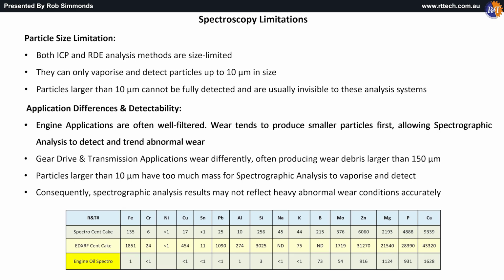Application differences and detectability. Engine applications are often well filtered. Wear tends to produce smaller particles first, allowing spectrographic analysis to detect and trend abnormal wear. Gear drive and transmission applications wear differently, often producing wear debris larger than 150 microns. Particles larger than 10 microns have too much mass for spectrographic analysis to vaporize and detect. Consequently, spectrographic analysis results may not reflect heavy abnormal wear conditions accurately.